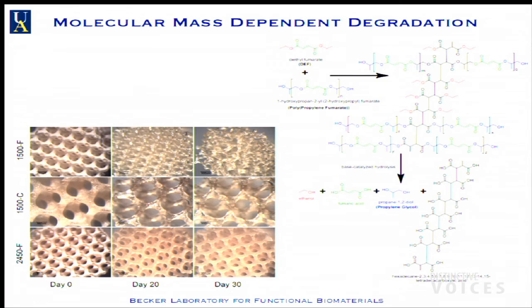And some of the chemistry is shown here, and if anyone has questions, I'll ask. But the key to this is that if the chains are short, even though you're creating covalent bonds between the chains, as long as what I'll call the chunk left over is smaller than 7 nanometers, which is smaller than your human serum albumin, which your kidneys retain, okay? As long as it's smaller than that, it will come out. Anything smaller than 7 nanometers will come out of your body through some active or passive process.